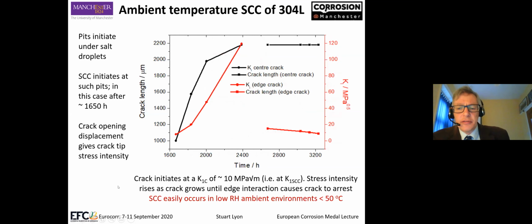So we turn that into a fracture mechanics approach. We find that the crack, in fact, initiates at a stress intensity of 10 megapascal root meters. That actually is the K1SCC for macroscopic compact tension samples. So it's exactly analogous to a macroscopic example. So stress intensity rises as the crack grows until edge interaction causes the crack to arrest. Essentially, that's a fracture mechanics interpretation of the crack arrest event. So the stress intensity rises, and as it hits the edge, it falls back to the level.